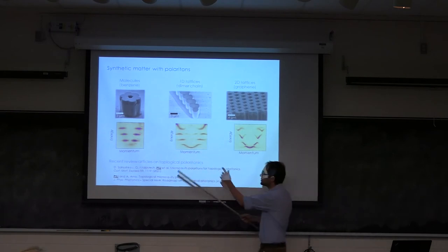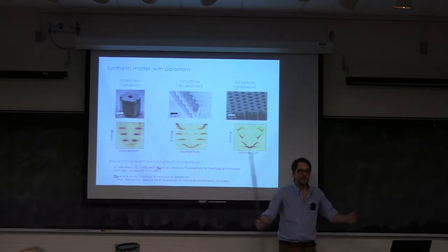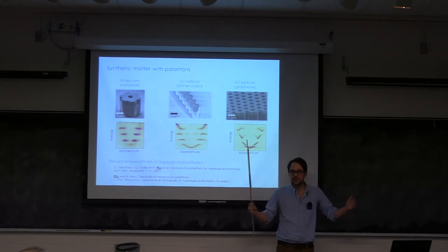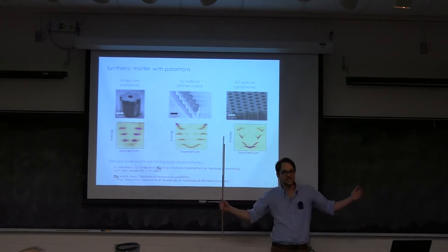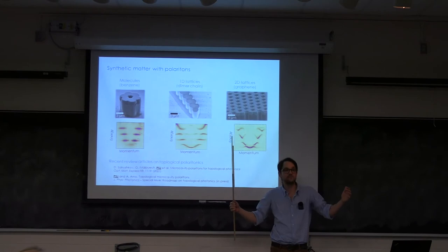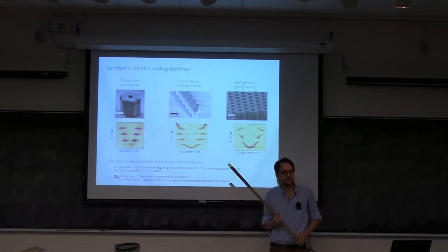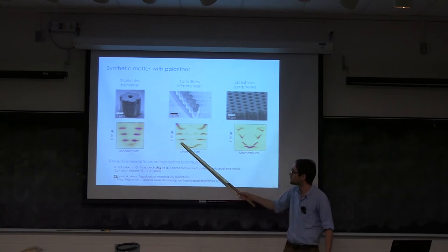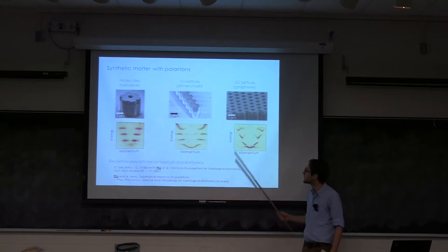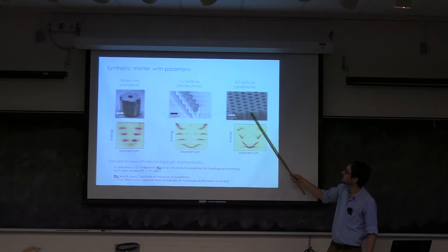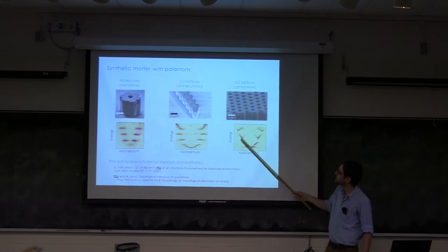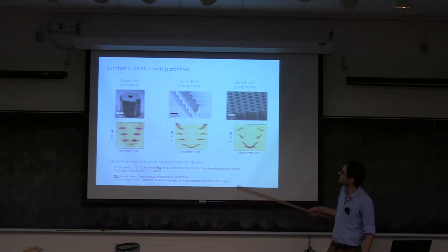But here you should notice that the Brillouin zone is much smaller, because the size of the unit cell is much larger than in the crystal. It's just an order of magnitude, just a number, but it is qualitatively the same as in the material. And we also have two-dimensional lattices. So this is a honeycomb arrangement that mimics the physics of graphene. You don't see them very well, but we can have these nice Dirac cones here and study the physics of these materials.